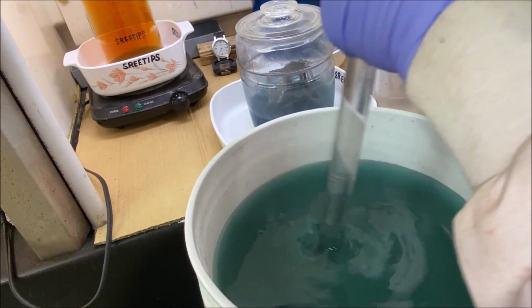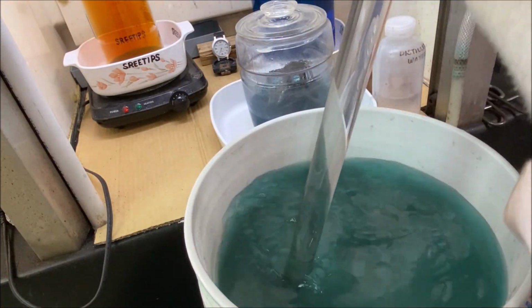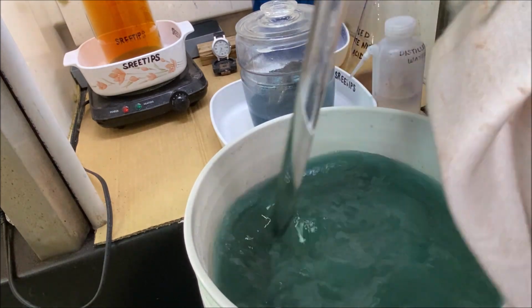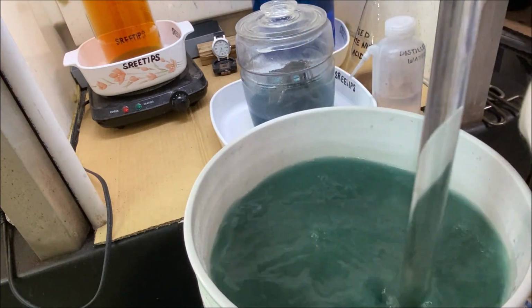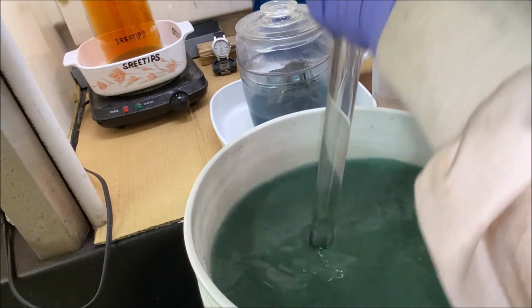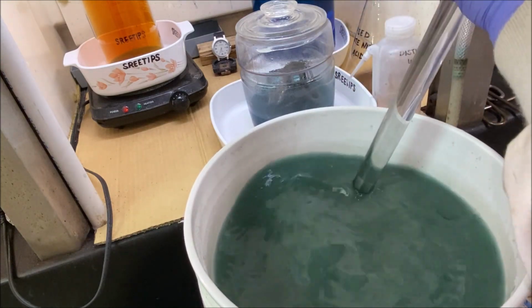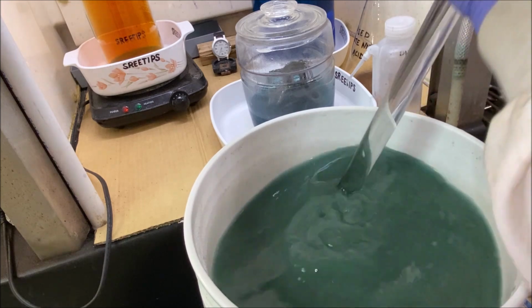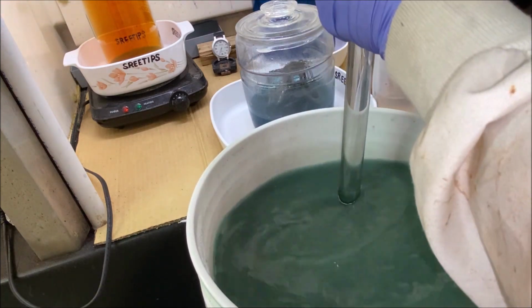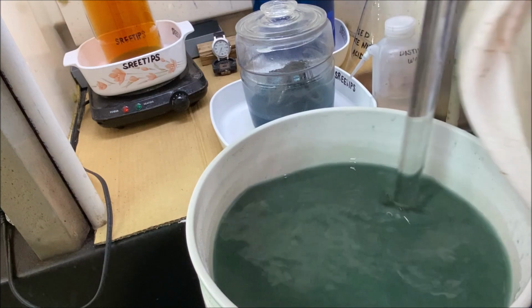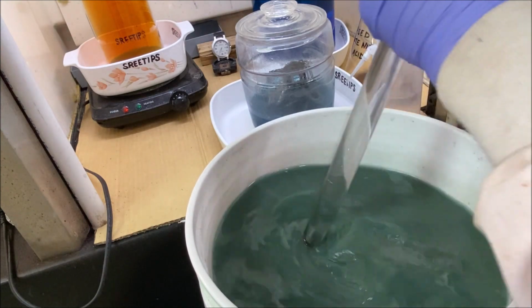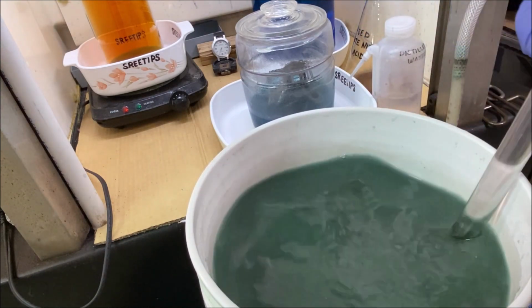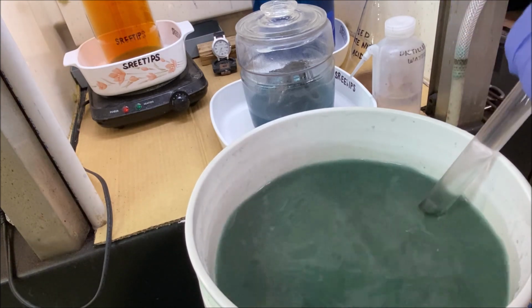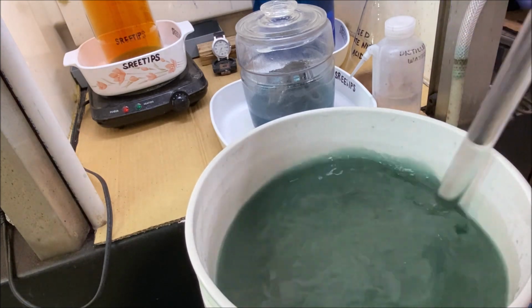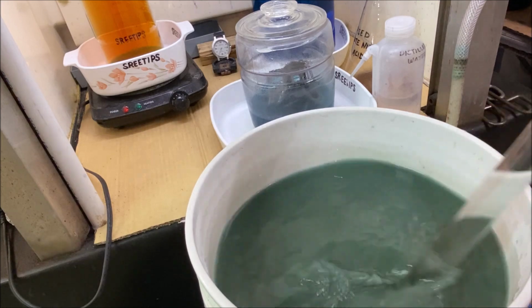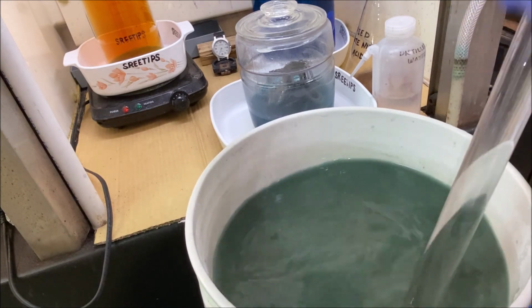All right, let me stir this up to make sure I get a fairly consistent mixture here. And we should have this stuff cementing out on the copper down there now. And this will take a while, probably take a couple days. Just leave it sit in here until no more reaction happens. And the copper gets consumed in this reaction. It goes into solution as the silver comes out of solution onto those pieces of copper in there.